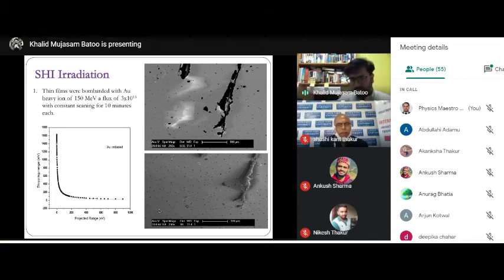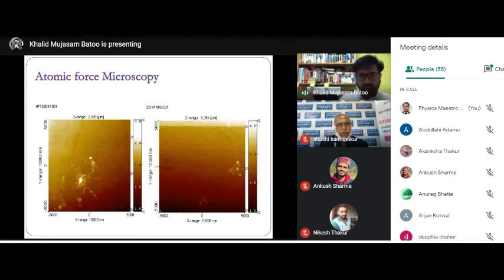The SEM shows a line or a scratch - it's almost a kind of columnar defect there. The atomic force microscopy shows there is roughness. Scratches are there in the film, showing the film is very rough.